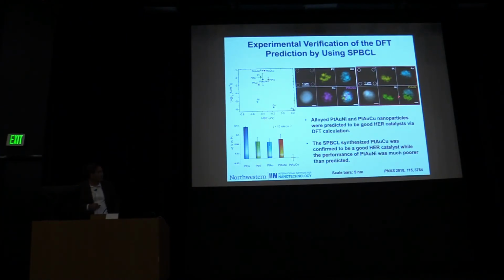You look over here, platinum, gold, nickel, you can tell in the index, the phase separates. It's actually platinum, gold in one phase and nickel in the other phase. Well, that makes sense, because we know platinum and gold's lousy, and we know nickel's lousy. So it's the fact that we got the alloy type structure here that we actually got the catalytically active one that works in this case. And so this ability to actually go back and cross-correlate structure with property and function, I think, is also important, because everything fits. Very difficult to do in solution.